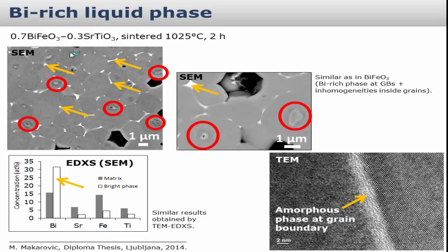At a certain stage, we had some phase rich in bismuth that did not react before we exceeded its melting temperature. So basically, you want it to react, but along the way, it will melt, segregate, and wet the grain boundaries, and this is how you end up with such ceramics.